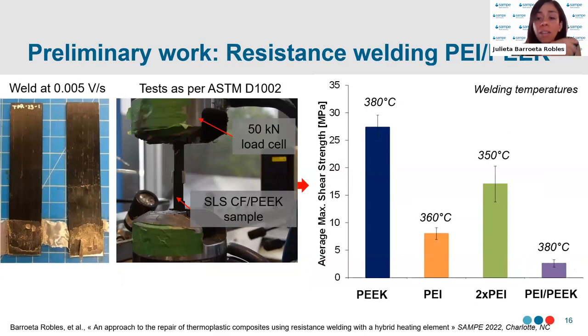To conduct these tests, the first step was to generate lookup tables. A thermocouple would be placed at the interface and a high temperature would be targeted, which would cover the entire processing range, in this case around 400 degrees Celsius. Then we were able to establish a relationship between temperature and voltage. I started targeting temperatures just above the melting temperature of PEEK and would break the specimens, targeting a failure that resembled what we see in this slide, cohesive failure, which was indicative of having attained a high quality weld. The ramp rate that was used was very slow to keep the specimens in contact for longer. After obtaining this failure mode, that temperature was targeted and a set of five specimens was welded and tested using ASTM D1002.